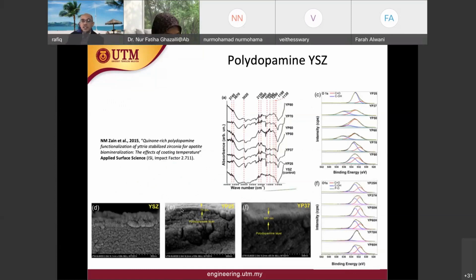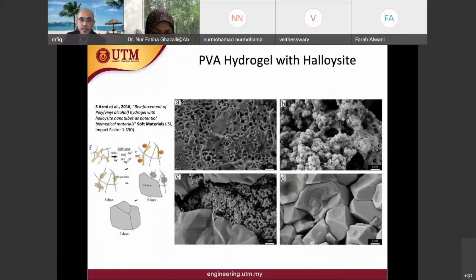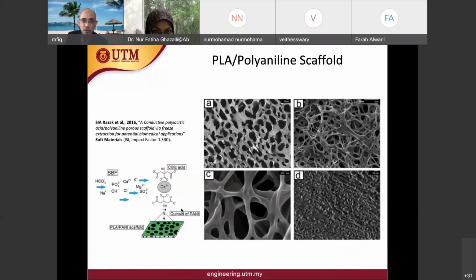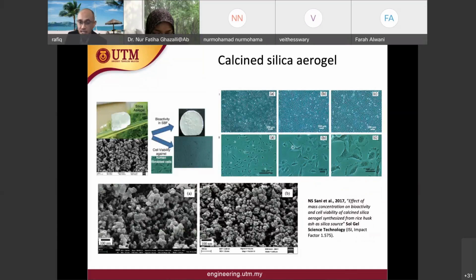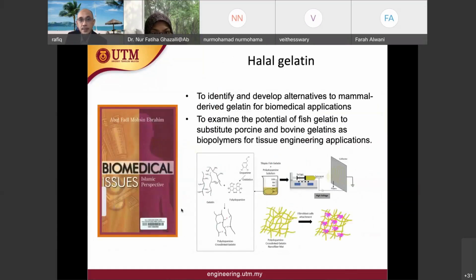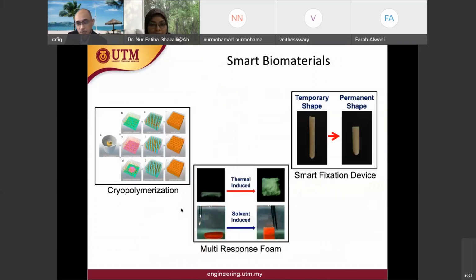This one, polydopamine, yttria stabilized zirconia, quinone-rich polydopamine functionalization of YSZ for apatite biomineralization, the effects of coating temperature, published in Applied Surface Science. And we also have PVA hydrogels with halloysite, PLA polyaniline scaffold. This is a scaffold using polymer-based material, PLA and polyaniline. We also have calcined silica aerogel work, and that's it. We also have some work on smart biomaterials that respond to heat.